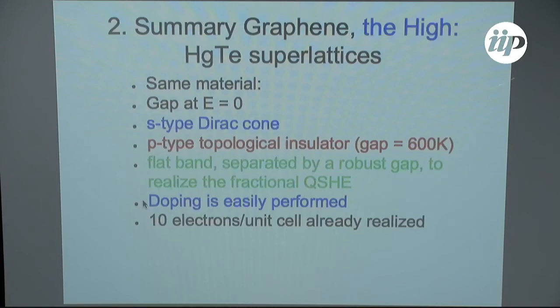So, summarizing this graphene, the high: we have been getting these mercury telluride superlattices, a material where in the same material you get a trivial gap at zero energy, an S-type Dirac, so you can do all the physics of graphene if you dope with one electron per site for the first Dirac, a P-type topological insulator, P-type in the sense that you have p orbitals, you are accessing p orbital physics, with a gap of 600 Kelvin. And we got a flat band, which is now separated by a robust gap from the other bands. This could be ideal to realize the fractional quantum spin Hall effect.